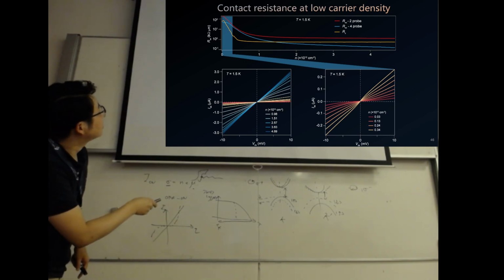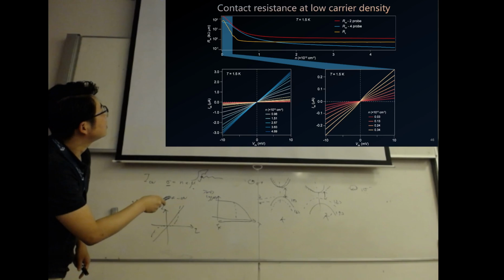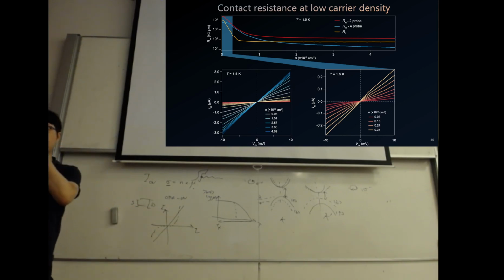And the boundary, let's say, defining this 1 kilo ohm above and down is about 0.3 times 10 to the 12. So below that, it's becoming bad. Above 0.3 times 10 to the 12, it's always ohmic. So this is a very low carrier density that can allow us to approach the quantum limit.